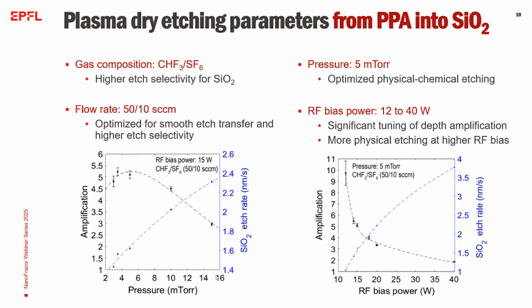First of all, during this plasma etch, the gas composition, flow rate, and pressure are the critical parameters for achieving smooth etching and optimal depth amplification. Particularly pressure control, as you can see in the left graph, is critical for achieving trade-off between the physical and chemical etching, which directly affects the amplification rate. And on the other hand, the RF bias power applied to the substrate is the most efficient parameter in controlling the amplification rates, allowing us up to tenfold increase in depth.